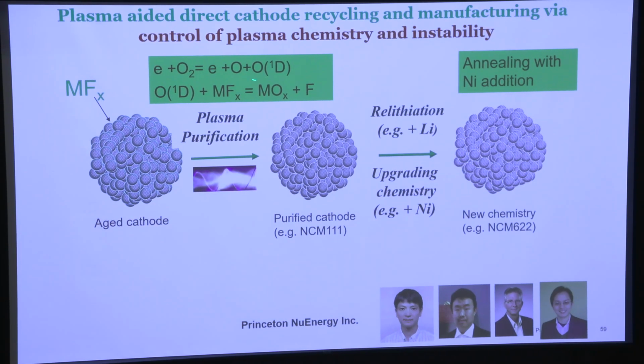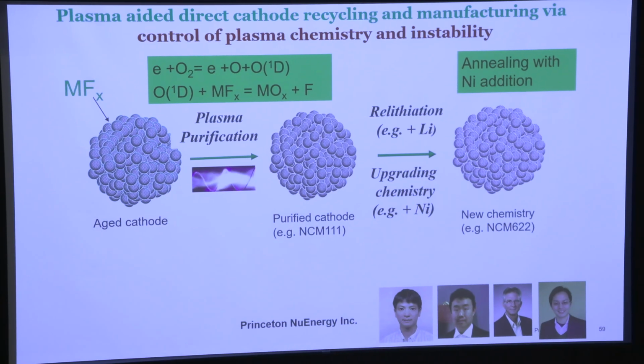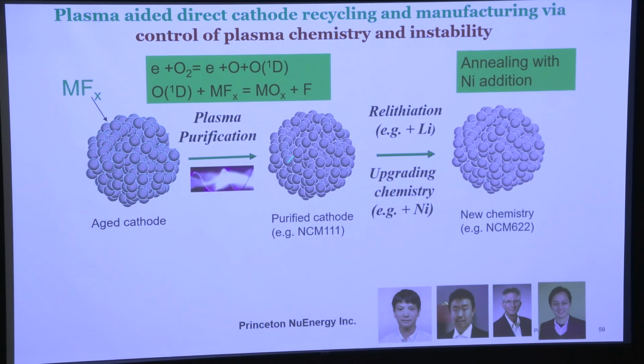So we thought, how can we use plasma to generate very reactive species like OH that can reduce the materials into metal oxide, so that we don't have to break down that electrode material into atoms? We just keep the same ceramic structure, but remove the fluorine and the carbon and many things, and then regenerate it. This is my postdoc Chao and my postdoc Xiaofang, and they created this company. And Bruce is my collaborator at Princeton.